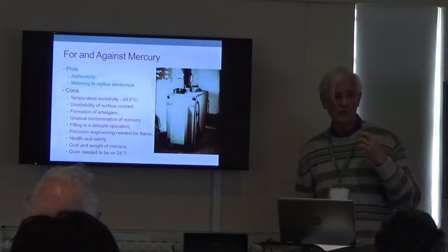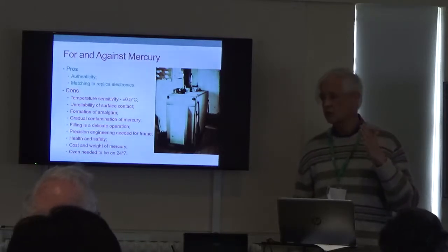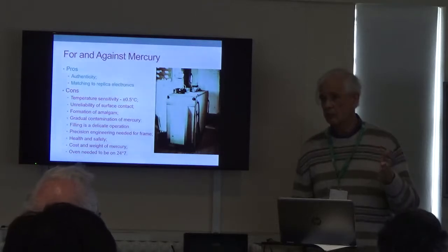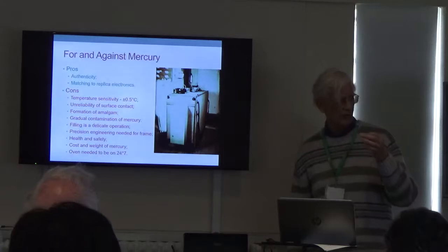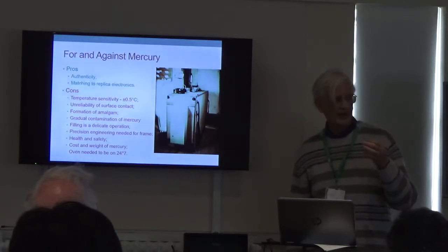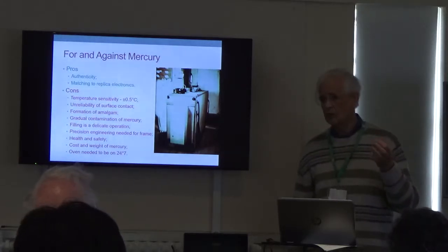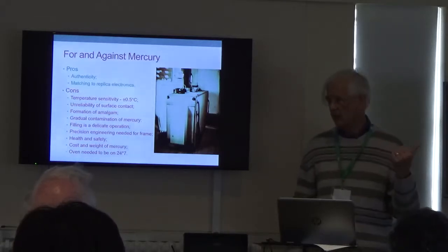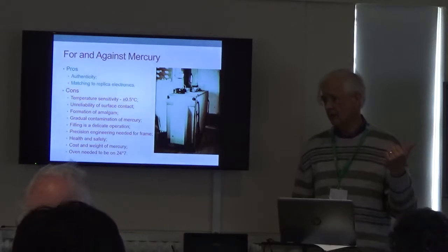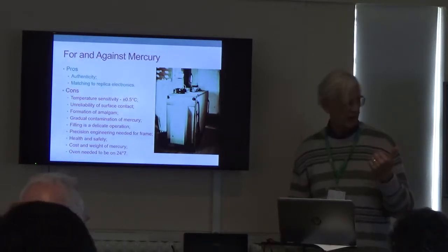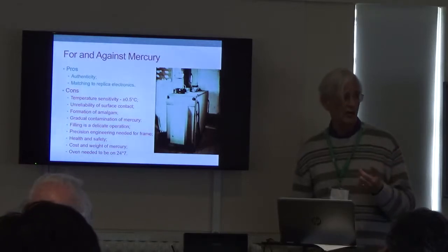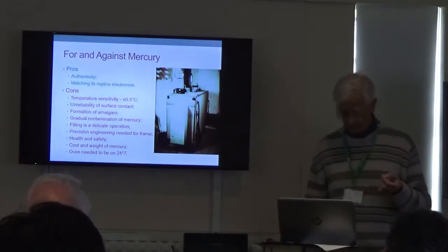You have to be careful also that the back of the quartz crystals do not touch the supporting blocks. These are Tufnol blocks, and if there's any trace of oil left on them from machining, you get an oil film and half the energy goes backwards out of the delay line the wrong way. And it stops working. So there are a lot of instances in the logbooks about tanks just stopping working and having to be overhauled.